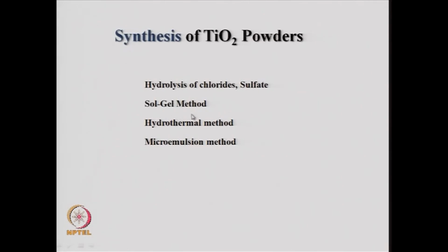used the sol gel method, which is a very popular method and we have discussed in our earlier lectures, or they have used the hydrothermal method where you use Teflon or steel containers to create a pressure in either aqueous medium or using a solvent, and some pressure is created and reaction occurs under pressure at temperatures around 100 to 200, 250 degrees centigrade, or maybe sometimes up to 300, 350 degrees centigrade.